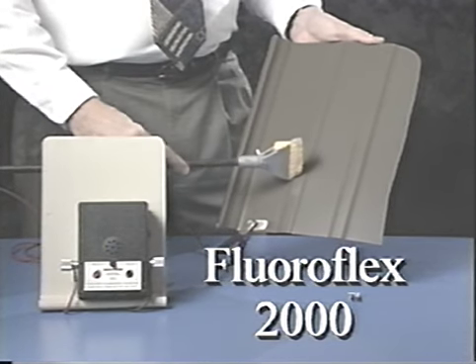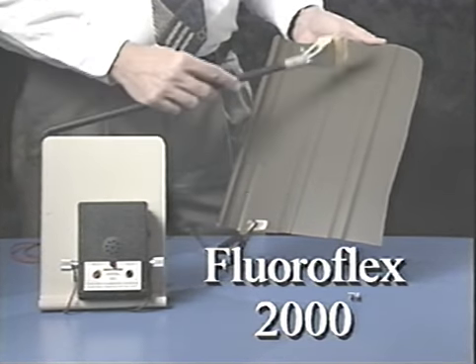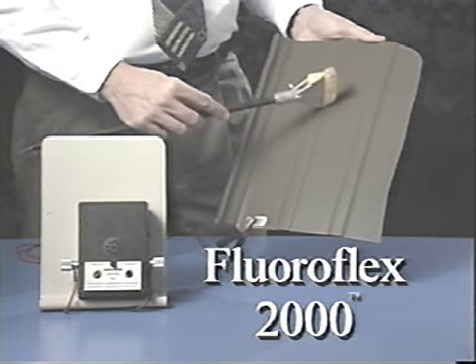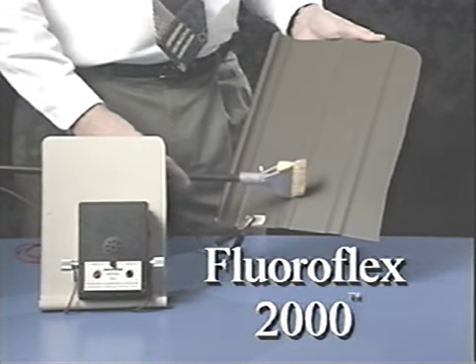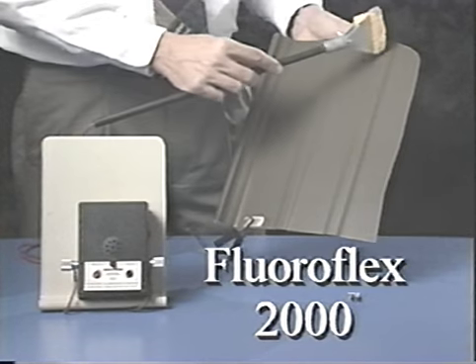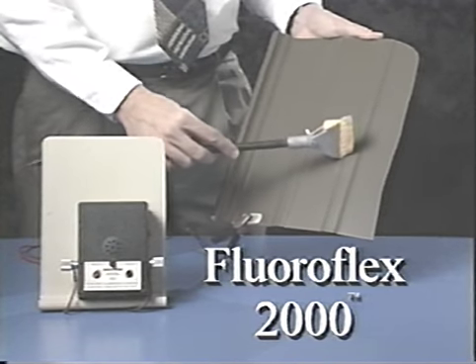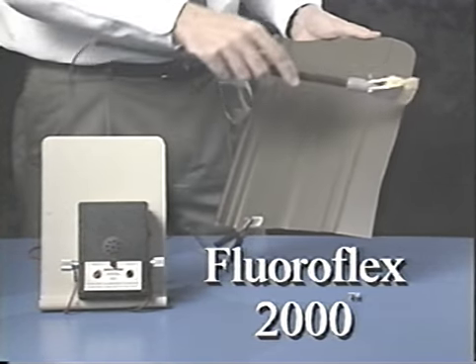This panel was formed the same way as the others, but as you can see, no paint film fractures are detected. Clearly, the Fluoroflex 2000 has effectively bridged any gaps caused by fracturing during the roll forming process.